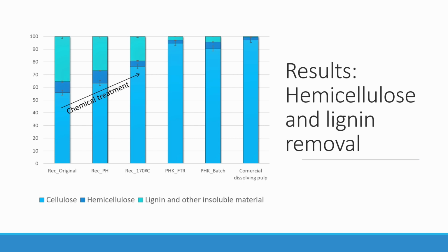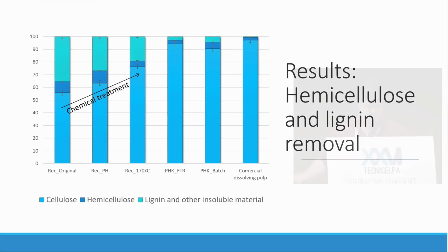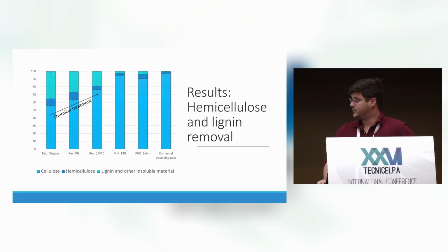So, starting with the hemicellulose and lignin removal. In the first part of the graphic, we have the results from the recycled pulp. We can see that with the treatment, the PREHYDROLYSIS and the KRAFT cooking applied to the recycled pulp, we have a decrease in the compounds that are not wanted in the dissolving pulp. However, they are still far away from the commercial dissolving pulp. When comparing the flow-through and the batch system employed in the PREHYDROLYSIS sequence, we can see that the flow-through reactor has produced pulps with higher cellulose content. That was one of the objectives and one of the interesting results of employing this PREHYDROLYSIS.